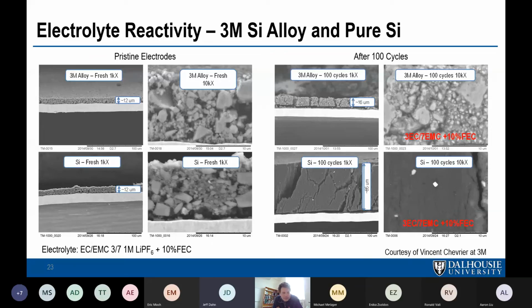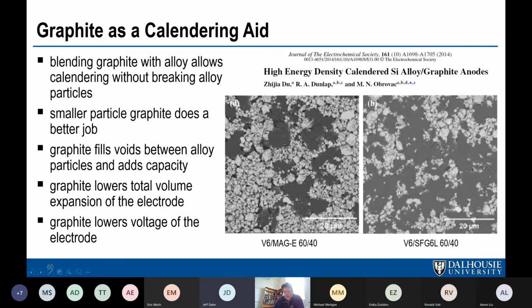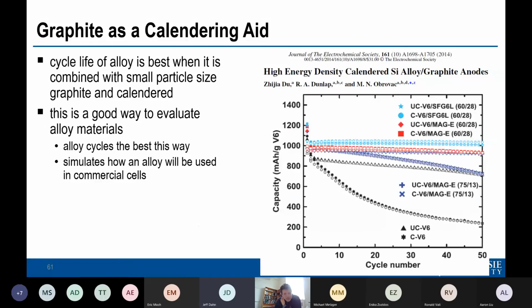Okay, well. Any more questions? Going once, twice? Quick one. All right, go ahead, Ron. So what's the highest practical silicon loading that's possible at the moment in a commercial cell? Well, that depends on exactly this here. How much graphite do you need to add to obtain a high density coating that can cycle well? This is unfortunately a weight percent, but this was 3M alloy. What was the density? It was around 3, I think, something like that. Anyways, you could have 60% by weight alloy and 28% by weight graphite, and still get